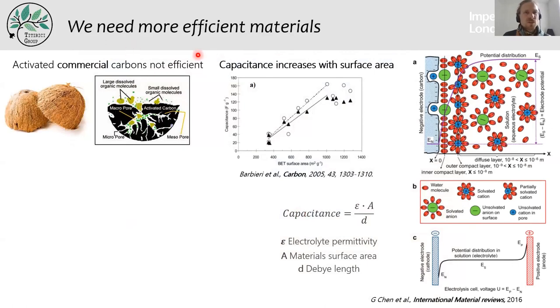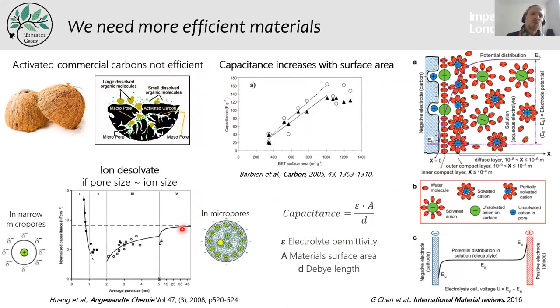And so we need more efficient materials. Activated carbon materials, the commercial ones, are not really efficient because their pore structure is not really designed for the ions. So recently, we used to think that the capacitance increases with the surface area of the carbons, as it's written in this formula here, with A, the material surface area. But actually, we discovered 10 years ago that the more you decrease the pore size, the more the capacitance starts to increase. And here the challenge is to create materials that have the right pore size to really maximize the capacitance.